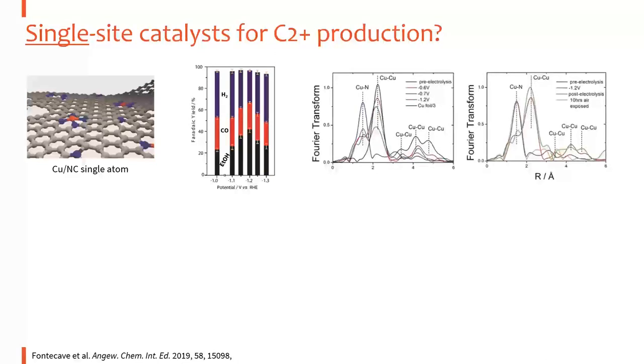Indeed, so how does the single atom catalyst work? They put their material under in situ conditions, that means under CO2 reduction working conditions, in X-ray absorption spectroscopy, which allows them to identify the copper oxidation state and the coordination environment. They found that before electrolysis, we can only identify the copper-nitrogen bond. But under applied potential, the copper-nitrogen bond decreases while, at the same time, the copper-copper bond increases. That means under reaction conditions, the single atom is not a single atom anymore. They aggregate into copper nanoclusters so that they have copper-copper bonds.